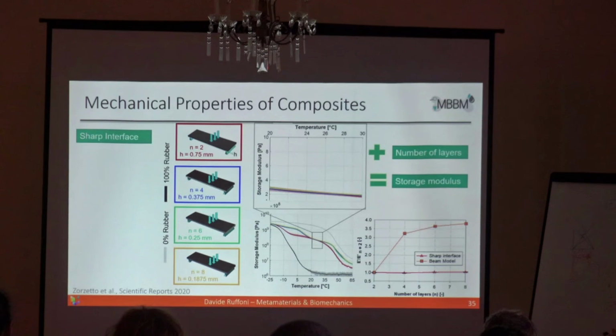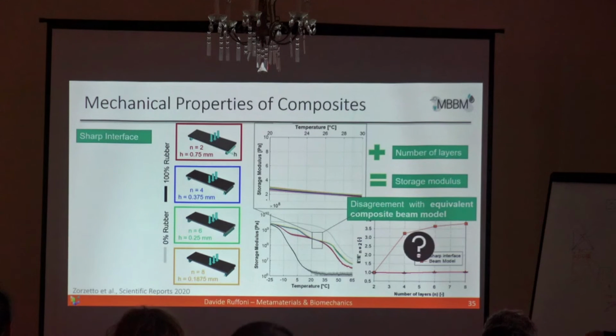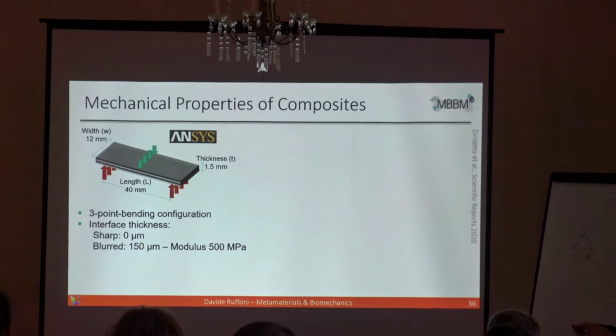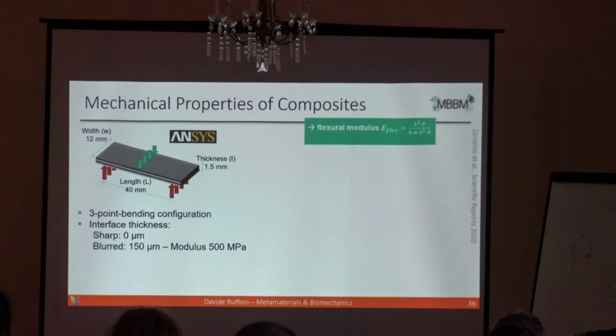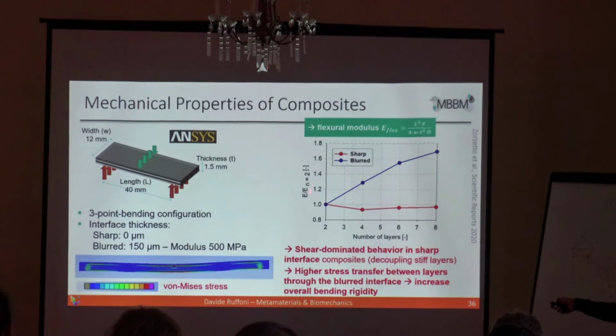Well, then, of course, we look a little bit in more detail into this. We did some finite element analysis, assuming 2 types of interfaces, very sharp and very blurred interface. And what we actually see is that the predictions of the finite element analysis were in agreement with the experiments.